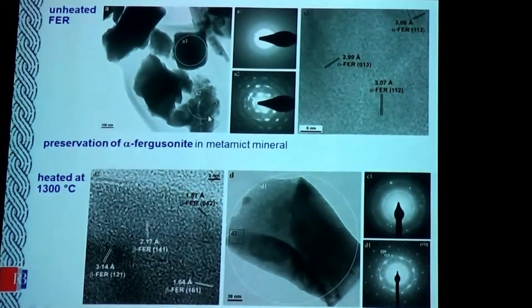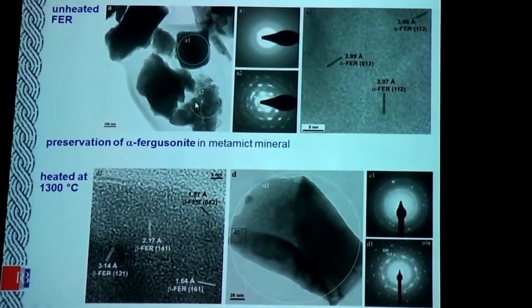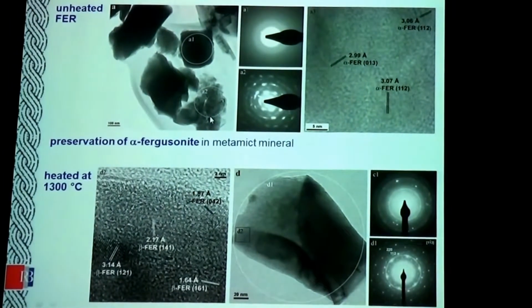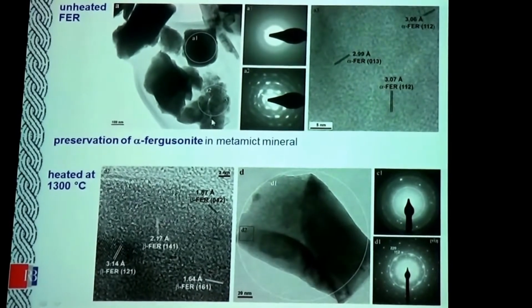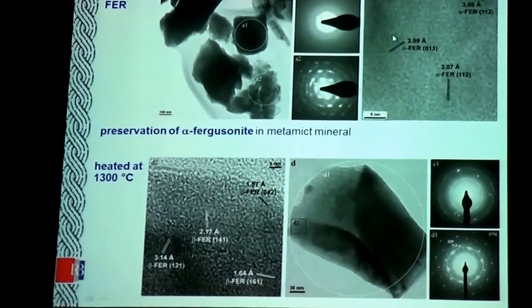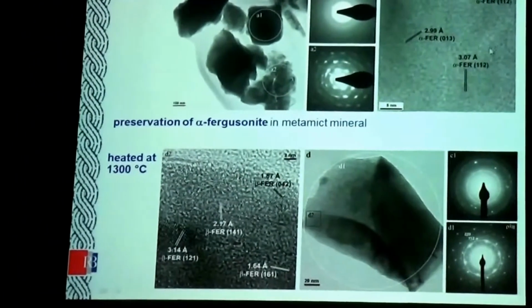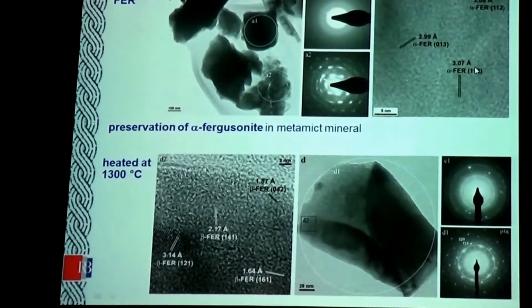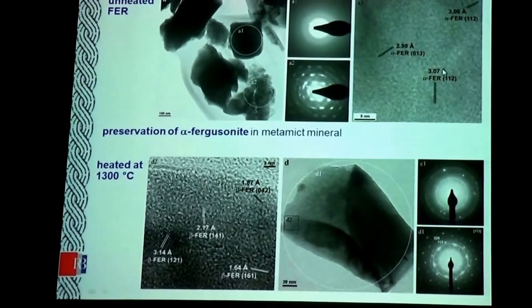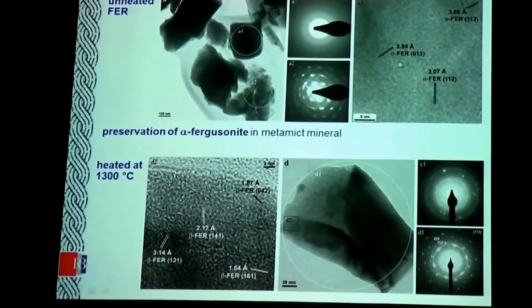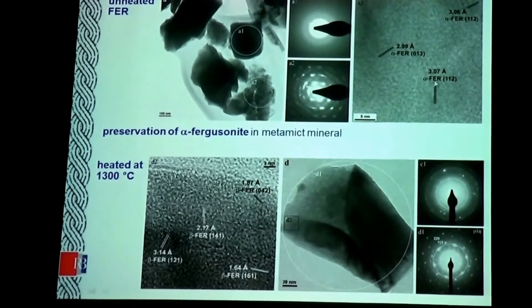So using TEM and electron diffraction, we find relics of original phases, and the relics show very easily that our finding with Raman spectroscopy was true, and that we really had alpha fergusonite.